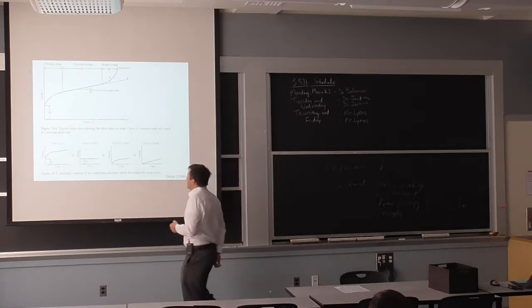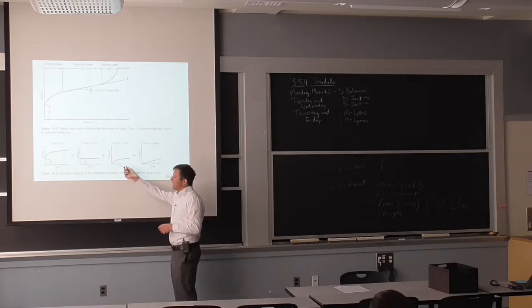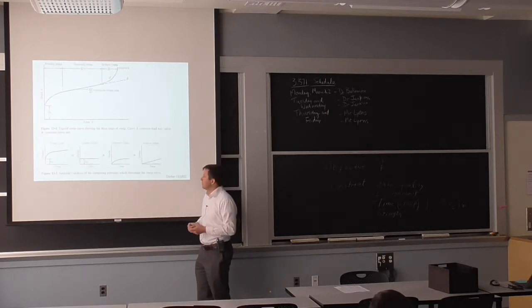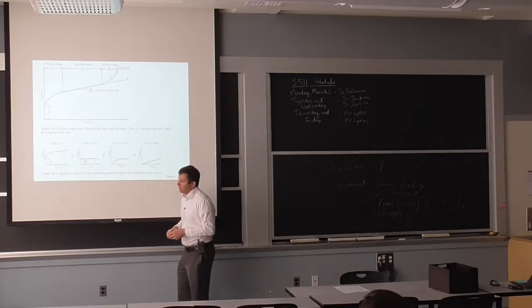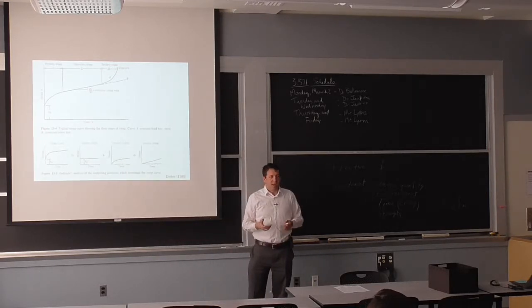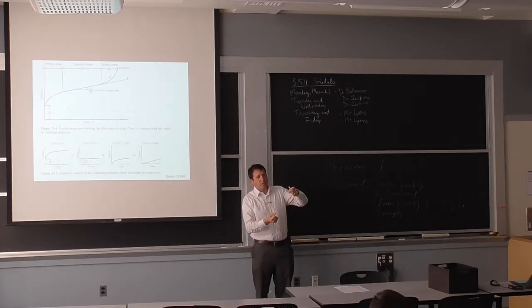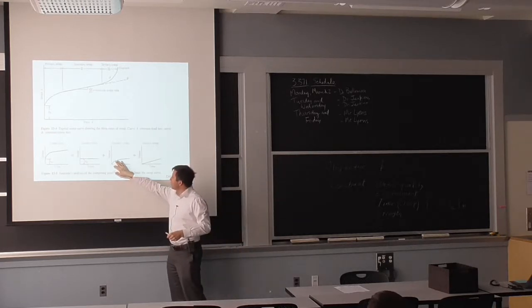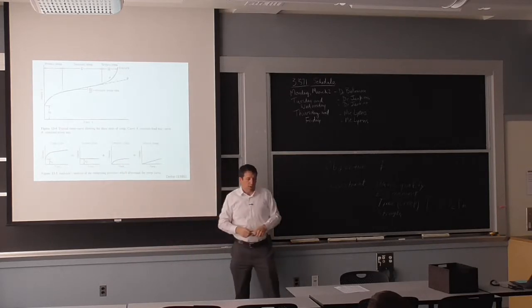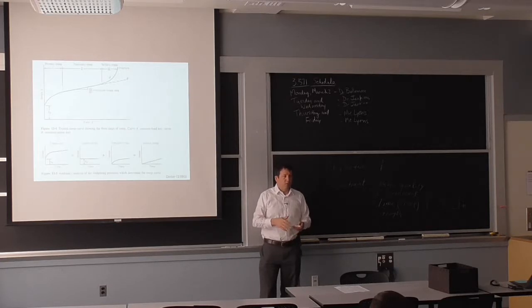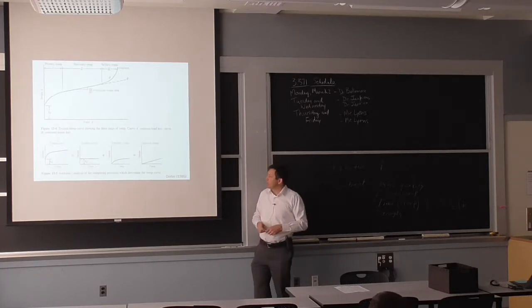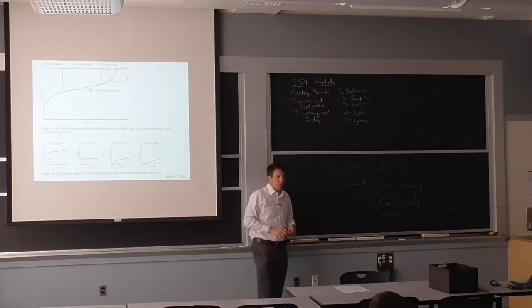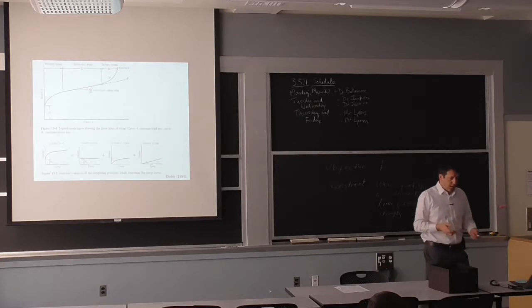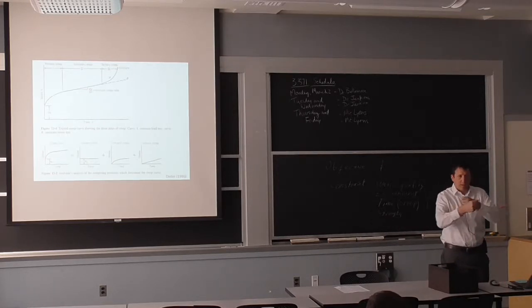So the behavior typically has two components, and that's actually very useful when you try to understand what is happening. The transient creep for polymers would be all that viscoelastic behavior. So you put on the load, and then it deforms pretty quickly, continues to deform quickly, and then it's slowing down. When it's slowing down, it's this transient creep that is stabilizing, but you'll always, with polymers, have some amount of continuation of that flow of the material, the deformation of the material, and that comes from the viscous component. And the viscous behavior, we'll see later that it's really the macromolecular chains that are moving one with respect to the other, and that's not going to stop.